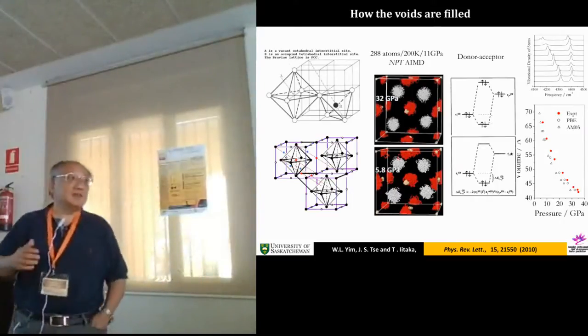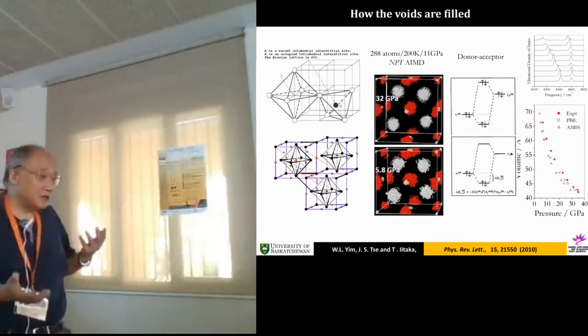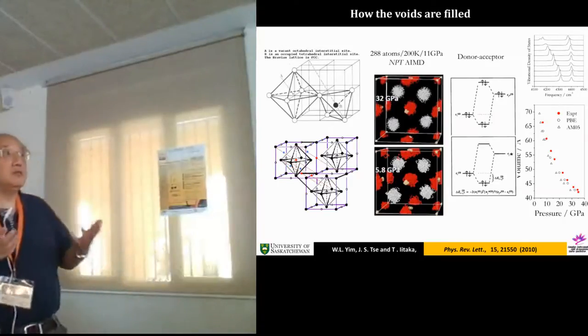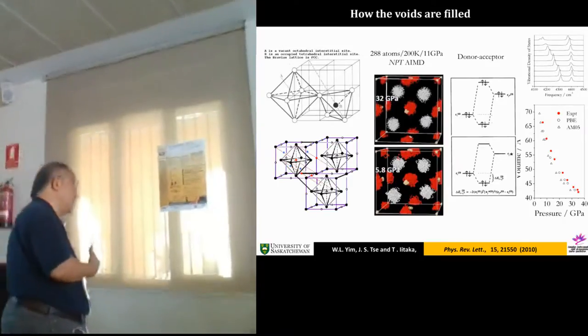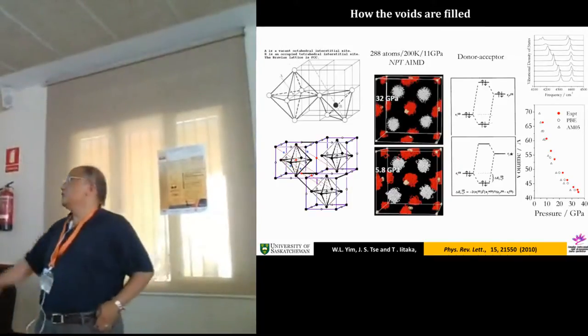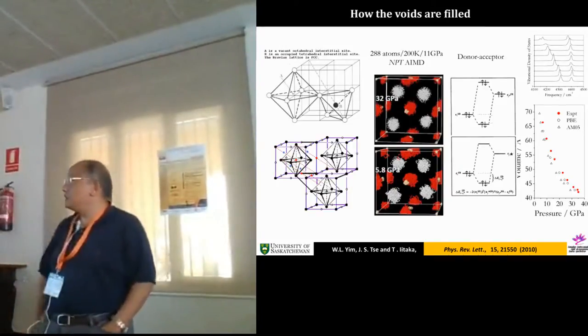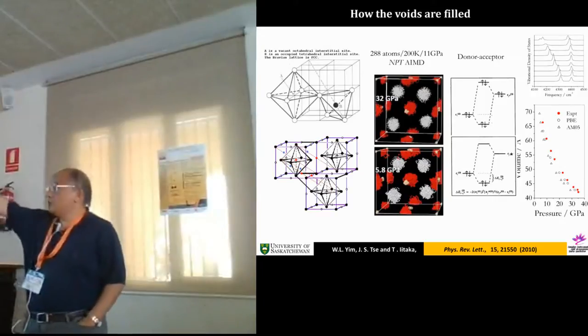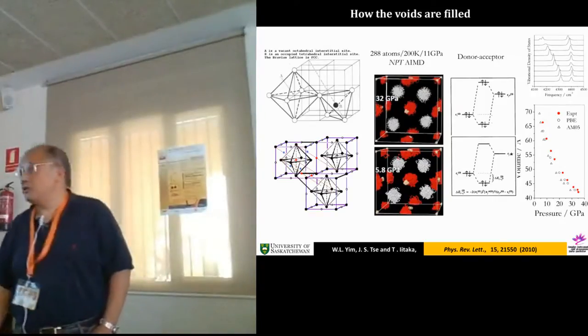lattice. It has octahedral sites and tetrahedral sites. What you can do is put the hydrogen either in the octahedral site or a tetrahedral site. It turns out it's in an octahedral site. They fluctuate a lot. There's an MD simulation at 32 GPa.